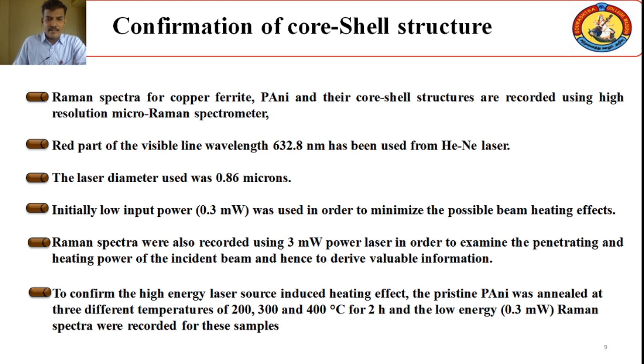Finally, to confirm the thermal energy induced during that high energy laser Raman spectra, we annealed the sample at 3 different temperatures, 200, 300 and 400 degrees Celsius for 2 hours, and we measured the Raman spectra at low energy, 0.3 milliwatt. We confirmed the presence of the core shell element. Actually, we tried different input powers starting from 0.1 to 4 milliwatt with a step of 0.1 milliwatt. So finally we concluded that these two characteristic input powers entirely distinguish the presence of the core shell structure.